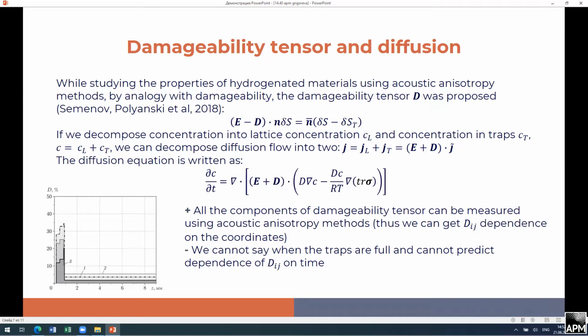So they introduced this tensor studying metal using acoustic anisotropy methods. And basically this tensor is a tensor form of the damageability, which describes how much of our initial surface, how much percentage of this is occupied with our traps.